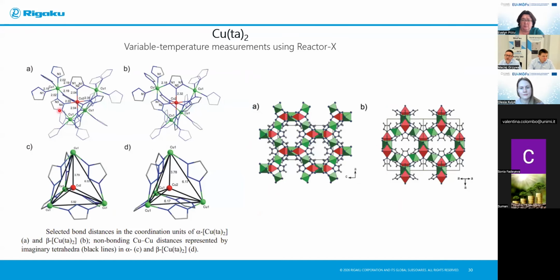If we check the distances between the copper ions and nitrogen atoms, we can consider 2 different copper ions in the structure. Here is the structure unit of the low temperature phase. We can consider two types of distorted octahedra. One is a flattened one, marked here with a green color, and the second one is an elongated one, marked with a red color. At higher temperature, this distortion disappears, and we observe equal bond lengths between the copper atom and nitrogen atoms as well. If we consider, for example, non-bonding copper ions, the distance in this high temperature phase is equal.